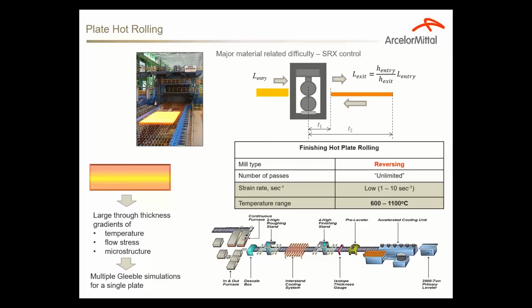Plate rolling, we also use the torsion tests to simulate the plate rolling. The plate rolling feature is that it is reversible. So the bar goes in the forward direction, and then in a reverse backward direction during rolling in one stand. The strain rates are low, temperatures are much wider, but one of the problems is the plates are thicker than hot rolled strips. So we have substantial through-thickness gradients of temperature, stress, microstructure, and we need multiple Gleeble simulations to set up the rolling of a single plate. We are working on the way how to reduce the number of simulations for plate rolling.